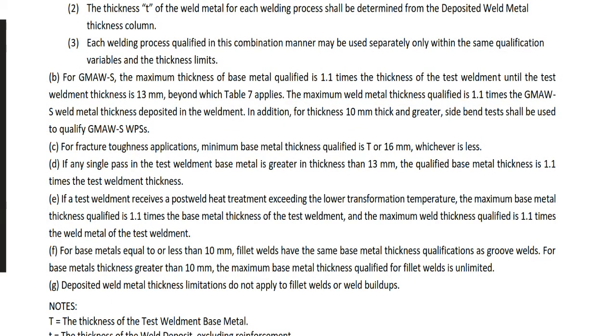Number C, for fracture toughness application, minimum base metal thickness qualified is T or 16 millimeter, whichever is less. So you select the smaller between T and 16 millimeter for what? Fracture toughness application. Minimum base metal thickness qualified.